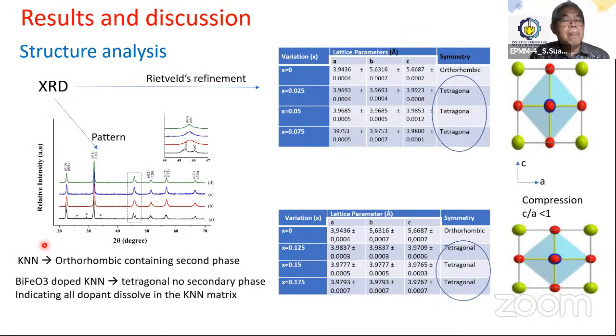Based on the XRD analysis, the undoped KNN has an orthorhombic structure containing a secondary phase. After bismuth iron oxide doping, our KNN becomes tetragonal and no more secondary phase is detected. That indicates that all dopants dissolve in the KNN matrix. Further analysis using Rietveld refinement confirmed that our samples have a tetragonal structure which is elongated for x equal to and below 0.075 and compressed for x greater than or equal to 0.125.